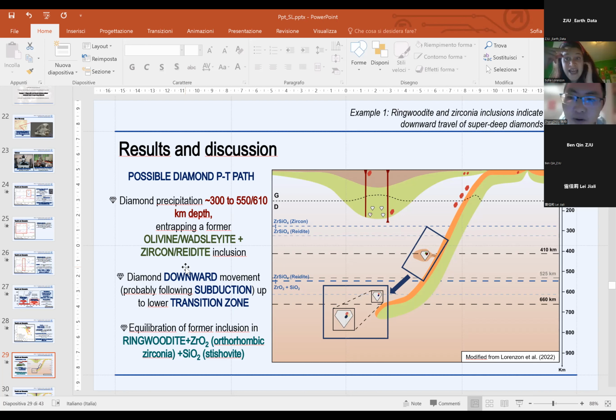We cannot determine precisely at which depth, but we determine a depth range between about 300 kilometers, which is the minimum depth for super deep diamonds, and 550 to 610 kilometers depth, which is the depth at which ringwoodite would transform into zirconia plus silica. And in this depth range, olivine, wadsleyite, and ringwoodite can be stable. In this way, we cannot determine perfectly which was the former inclusion that our diamond entrapped. But we suppose that the entrapment occurred in this depth range and entrapped one of these four mineral phases.